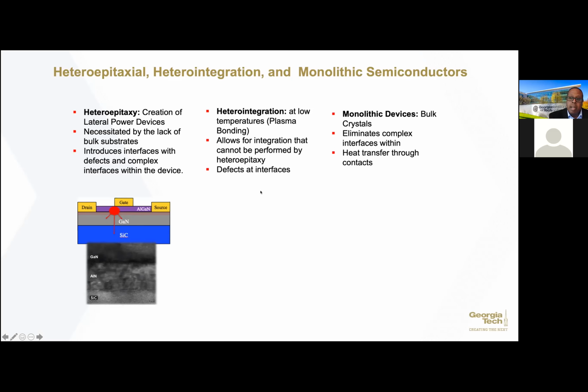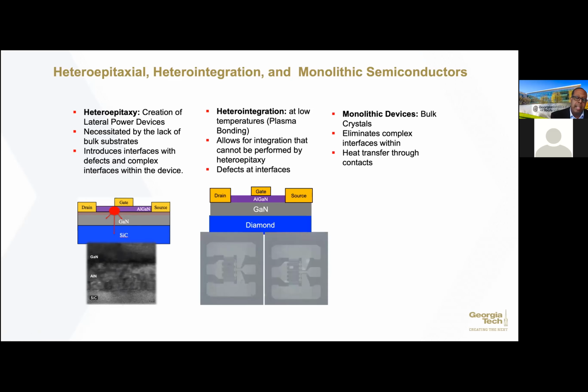There's also hetero-integration. So now I can place a material such as GaN on top of silicon carbide or a diamond without growth. And this is done using things like plasma activated bonding. And so this gives me a different way in terms of manufacturing, in terms of how can I put these two materials together. I can separate the optimal growth of the two materials and then place them together through a bonding method. And it doesn't necessarily require the same control that you have in terms of placing these inner layers.